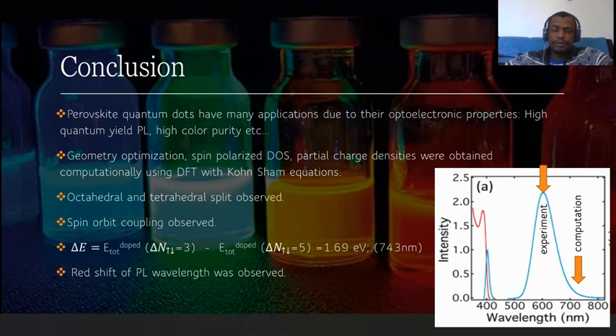So in conclusion, we understand that perovskite quantum dots have many applications due to their optoelectronic properties of high quantum yield and high color purity. We did the geometry optimizations, spin polarized DOS, partial charge densities using DFT with Kohn-Sham equations, and we also saw octahedral and tetrahedral splits and spin orbit coupling as well. We extracted the energy and confirmed that the photoluminescence was redshifted, and yes, that was all. Thank you very much, and if there are any questions, I would be happy to answer.